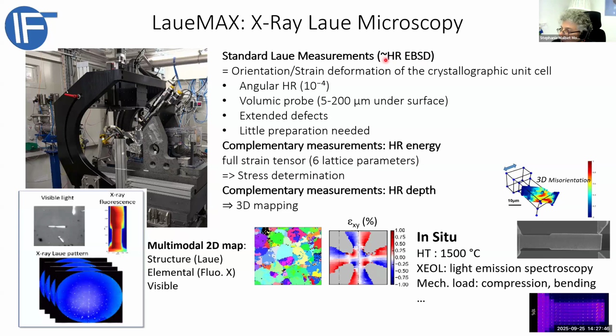But in our case, this is easily done with a high resolution in terms of angles. So we can retrieve the local orientation and strain at any point on your microstructure. So every half micron, let's say, you can get the orientation and the strain, the lattice parameters of the unit cell, with a very, very high resolution. Thanks to the penetration of the X-rays, you can really probe under the surface. And this is very satisfactory because sometimes the first nanometers or the first micron of the surface could be degraded, but the properties are explained by the inner part. You can have an idea of the plastic defects that can happen in your materials.